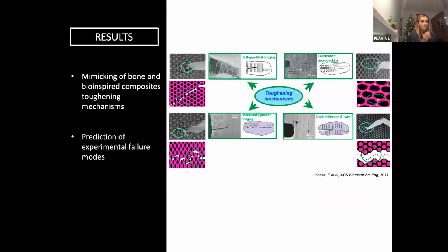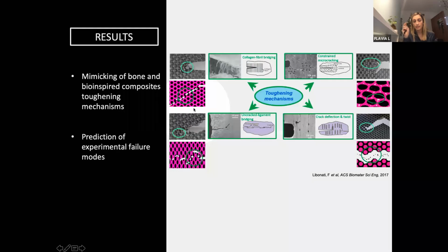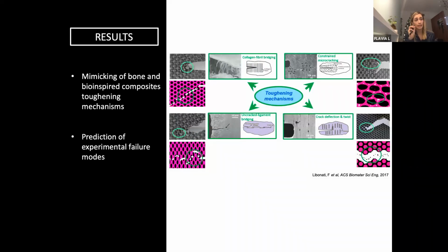So summarizing here, what you can see is that with this kind of method, we can actually mimic all the bone and bioinspired composite toughening mechanisms. What we can see here is a one-to-one comparison between the toughening mechanisms that we observe in real bone. Here you can see the schematization, a picture of the real bone, but also a picture taken on our experimental 3D printed specimen, and then the virtual testing, so this in silico testing. And you can see that in the end, we were able to mimic all these toughening mechanisms.